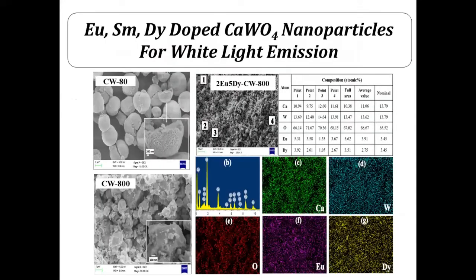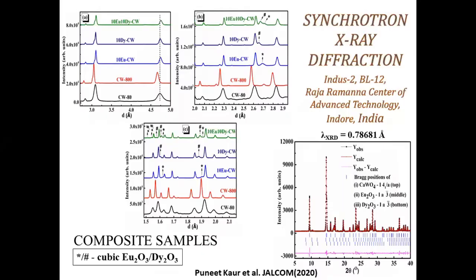And we do energy dispersive X-ray analysis to see the surface morphology, and also to measure the concentration of calcium, tungsten, oxygen, europium, and dysprosium ions in the lattice. And the concentration is fairly uniform. So there is no segregation, there is no clustering of the rare earth ions in the structure. And these are again the X-ray diffraction patterns, and very high resolution XRD studies were done using a very strong X-ray source of wavelength 0.78681 angstrom. So it is a purely monochromatic X-ray source, unlike a laboratory X-ray source, where you use a copper tube that has both copper K alpha 1 lines and copper K alpha 2 lines.